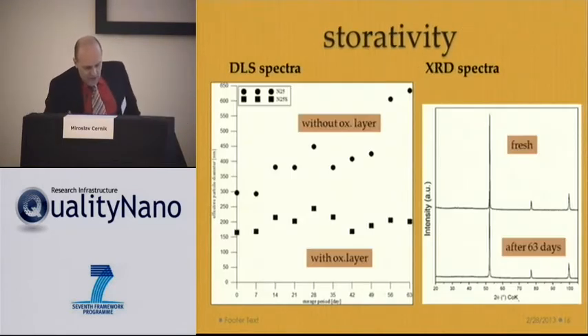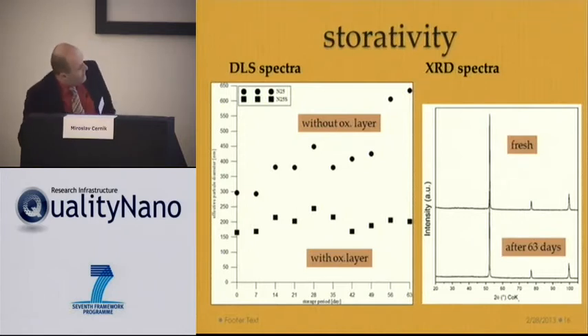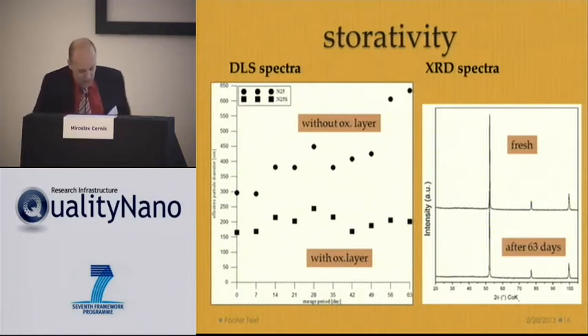The other parameter is the storativity. We need to have particles which survive for some period of time, and here we have two examples: the particles without and with this oxidic layer. And this is the DLS spectra showing that the mean particle diameter is more or less constant with this oxidic layer. And here is the Röntgen spectra showing that for the fresh particles and the particles after 63 days, the spectrum is not different, so the particles are almost the same when they are stored on air.